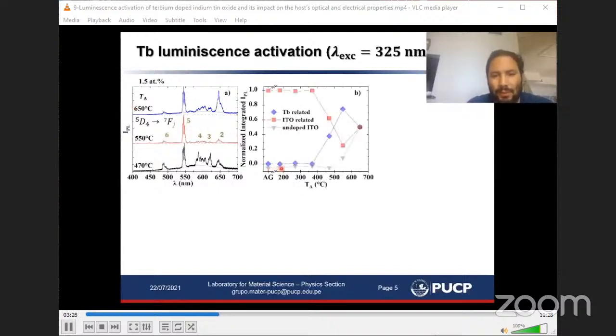Concerning the integrated emission intensity, we see that the emission intensity associated to terbium increases with annealing temperature till a certain temperature, and then it decreases again. A similar behavior is observed for the host-related emission of the same sample. We believe that this variation is associated to an effective competition between the recombination and subsequent energy transfer to host-related states and terbium states. We believe this because when we monitor the emission of an undoped ITO sample, we see that the host emission increases with the annealing temperature, meaning that we might be activating other recombination paths and luminescence centers associated to the host.